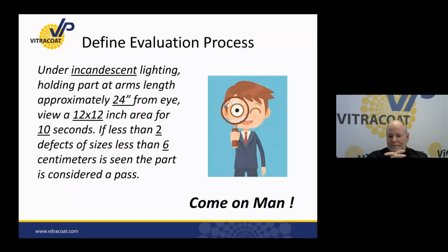So I'm going to read it. I've got a powder operation, and this is how we quality control the parts that are coming off my line. Under incandescent lighting, holding the part at arm's length, approximately 24 inches from the eye, viewing a 12 by 12 inch area for 10 seconds, if I see less than 2 defects of size less than 6 centimeters, this part is considered a pass. Now you can fill in the blanks.